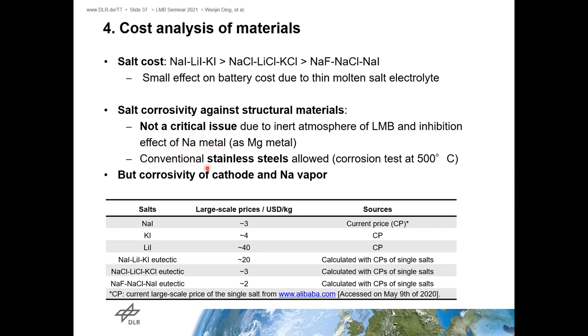Regarding the salt corrosivity, conventional stainless steels can be used. We also did the corrosion test at 500 degrees C, and it also shows no problem. But maybe the problem is the corrosivity of the heavy metal cathode and also the sodium vapor. So we need more study in this area to ensure the battery's safety.